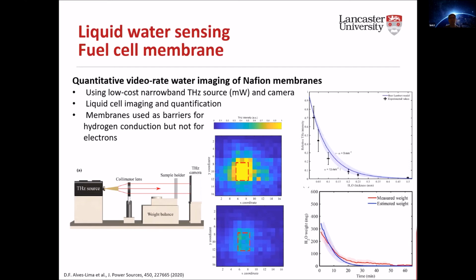So it's good that we can qualitatively see this, but what's probably more exciting is if we can start to quantify the amount of water there is from a light measurement. And so what we did was start playing around with different water thickness, and this corresponds to these dot points, plotted against a backdrop of Beer-Lambert's law. What this means is that from a relative terahertz measurement, you can start estimating the water thickness.